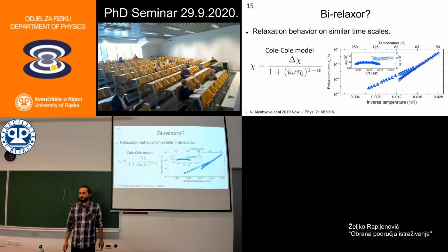But can you estimate the distribution? How broad is it? How much, 100%? Or can you estimate from this number? There is a derivation of this formula with some integrals, and then you have a distribution function, and from the width of this distribution function you get this alpha in principle. So you cannot exactly calculate, but you can estimate the broadening.